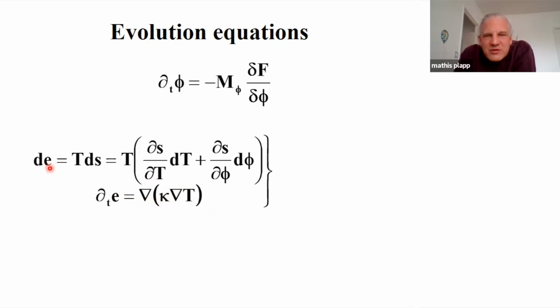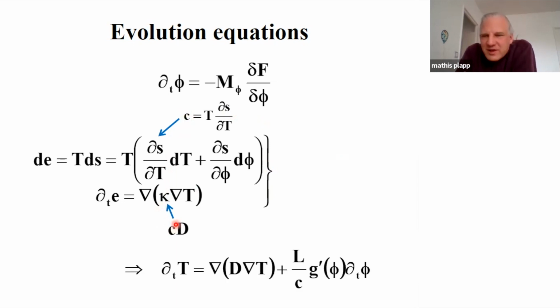And on the other side, I can use that I have my first law of thermodynamics. If my density is constant, then the change in internal energy is just TdS. And the entropy actually depends on the temperature and on the phase field. So I use the chain rule and I get that I can express the variation of entropy in terms of temperature and phase field. And now if I use various thermodynamic identities, namely this identity for the specific heat and this decomposition of the heat conductivity in terms of the heat diffusivity, I get an equation for the temperature, which has a diffusive part and a heat source part.